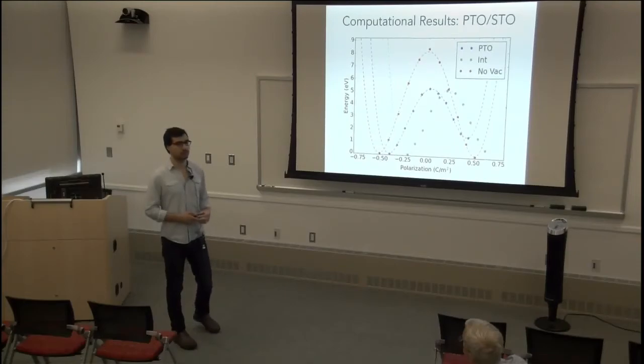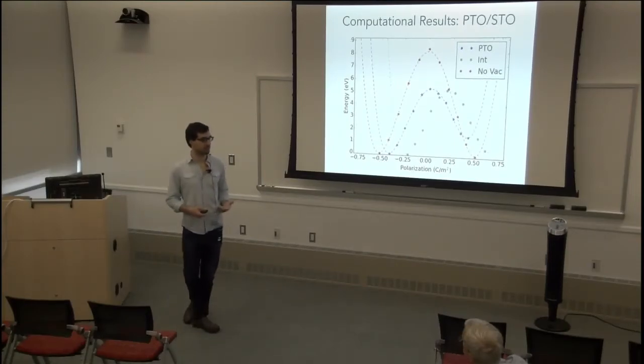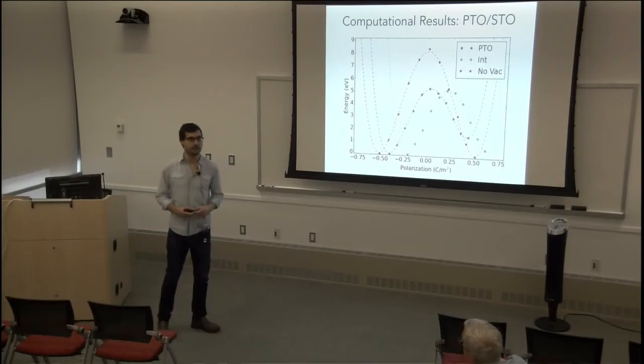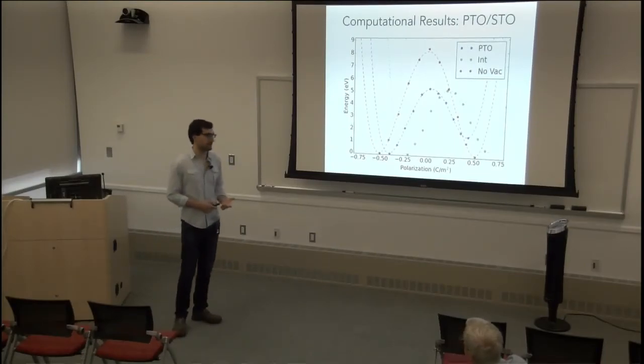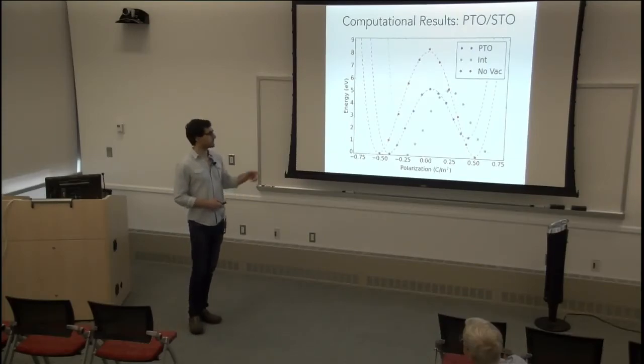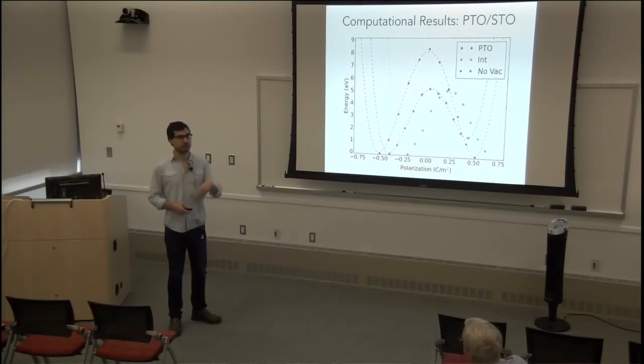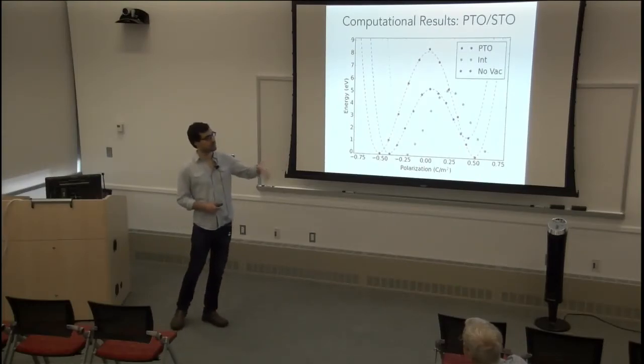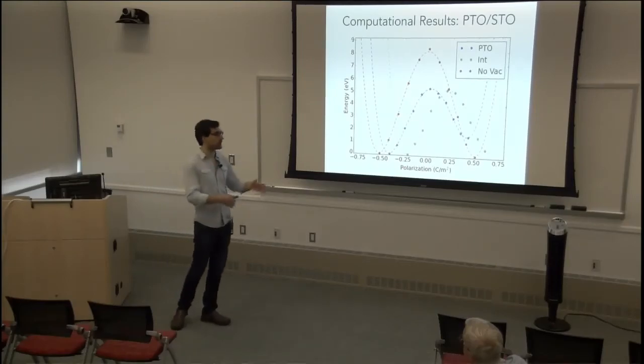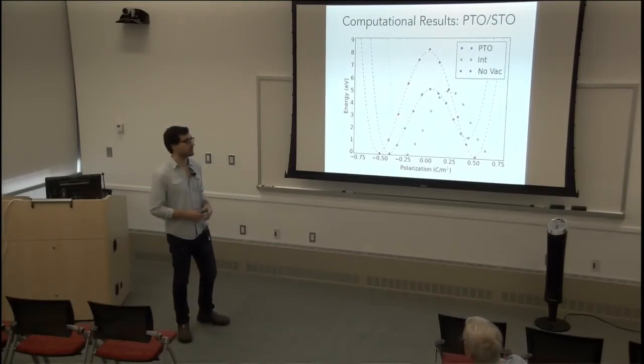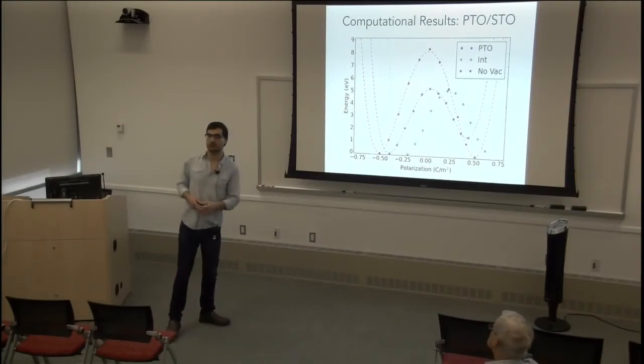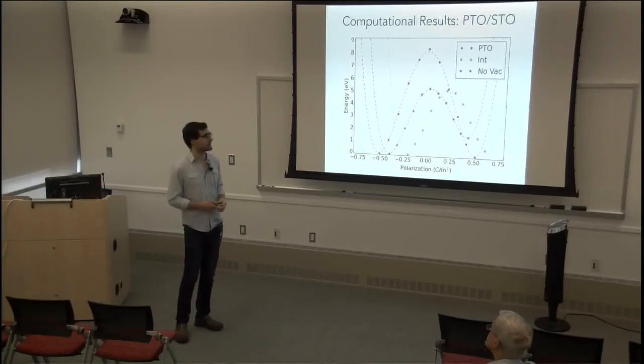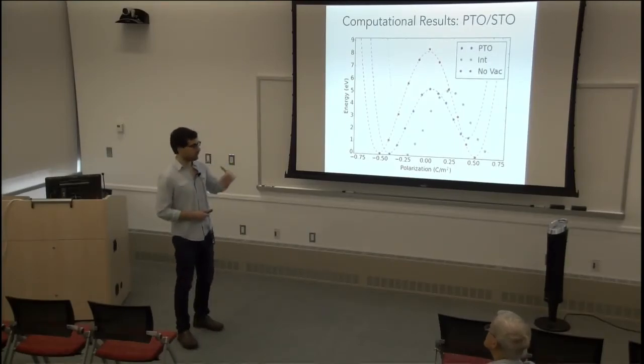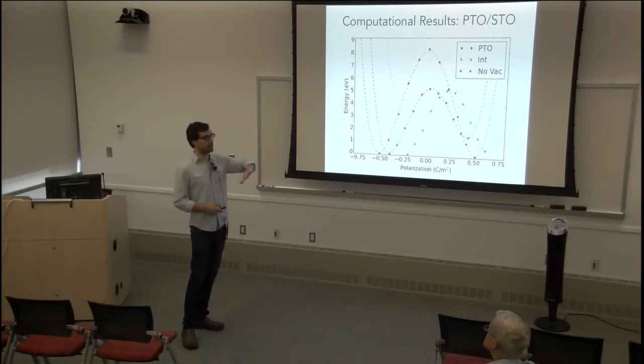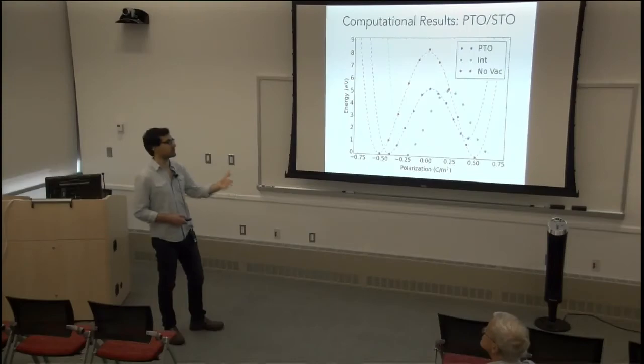it's not something that you would be able to get directly; you would have to make some sort of hand-waving argument about the concentration of oxygen vacancies that you have. They know for a fact that they do have it. There are some measurements where they keep running the hysteresis loop like 1,000,000 times, and then they see that the bias decreases, and they know this is because there's a migration of oxygen vacancies. So they know for a fact there are oxygen vacancies, even though these superlattices are grown using state-of-the-art techniques. They know for sure that there are oxygen vacancies, and we indirectly observe that when they move to the electrode, the bias decreases, so they must be responsible for the bias.